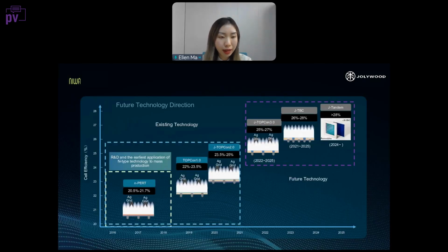Also, Jolywood is the first company in China to put N-type technology into mass production. The first generation we had started from 2016. At that time, the technology we used was n-PERT, and the efficiency was around 21%. Although it looks very old now, in 2016 this efficiency was actually very high. And then we came to the 2019s. From this year, we successfully upgraded from n-PERT to N-TOPCon, and the efficiency significantly increased to around 22% to 23.5%.